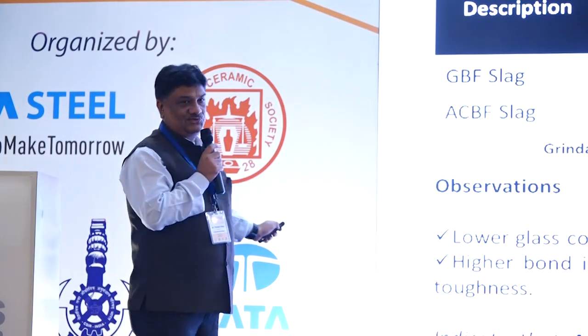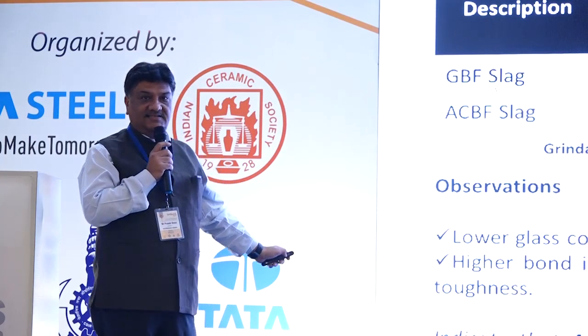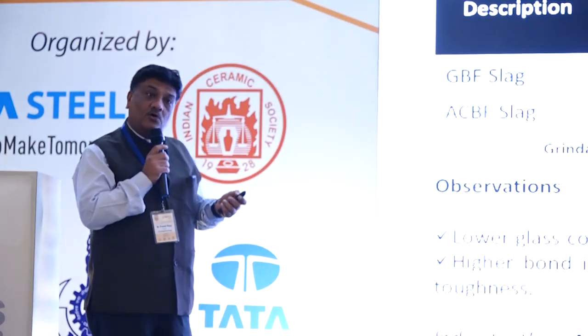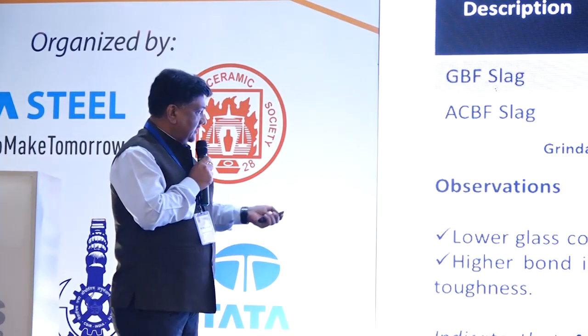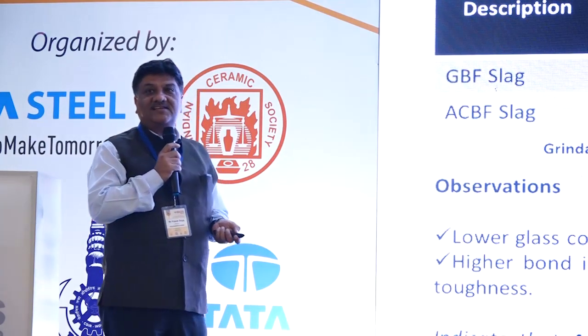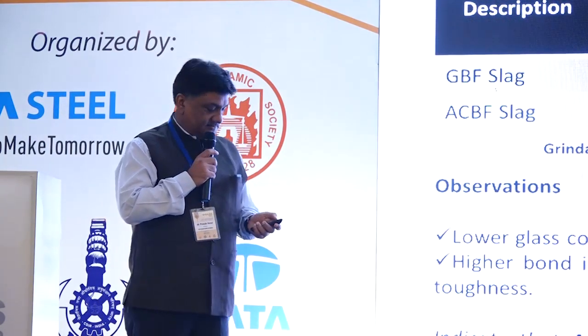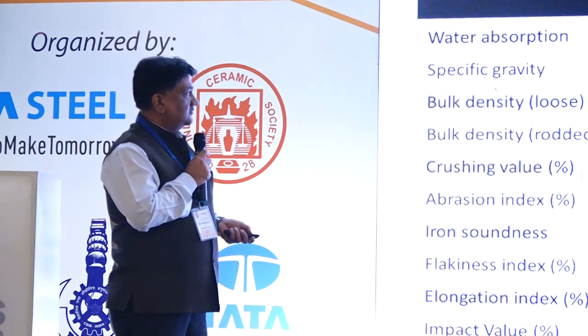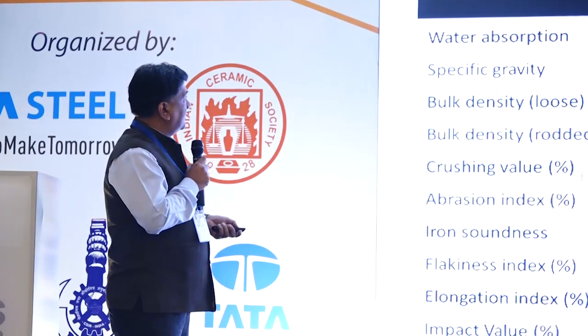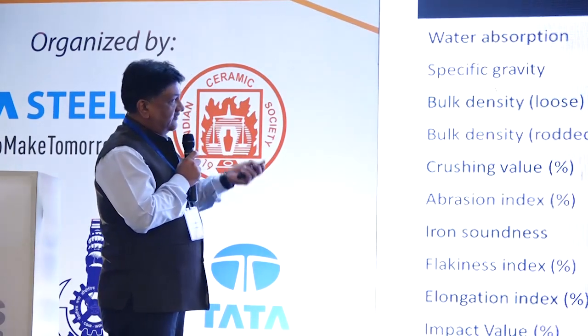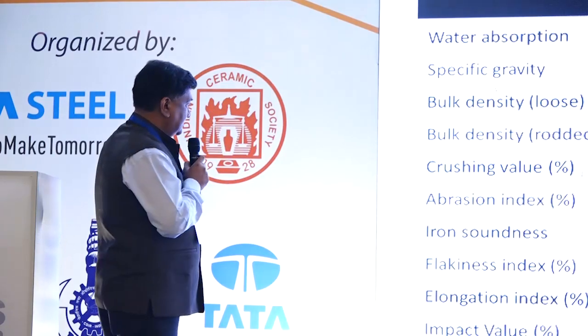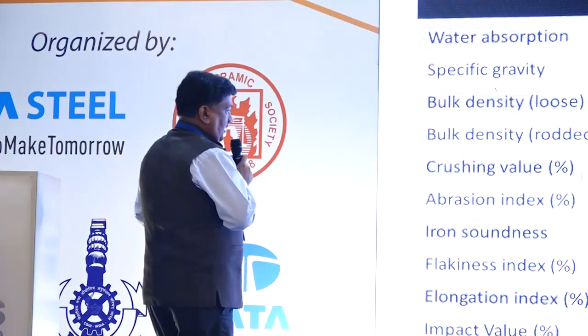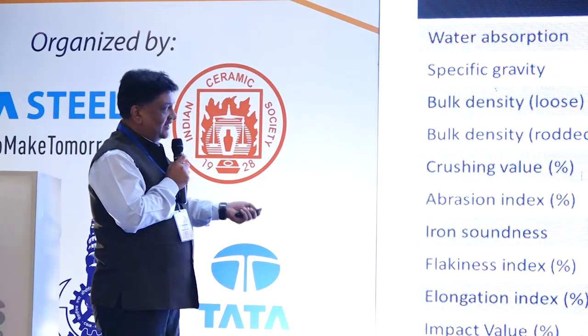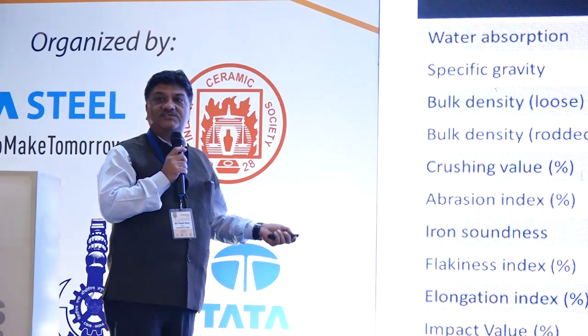So there is a challenge using GBF slag as an SCM, maybe for cement production, or as an SCM for concrete production. But of course, there's a huge opportunity to use it, replacing fine aggregate. Code compliance has been checked with the same aggregate which we got from TSL Jamshedpur. There is a clear indication that we can definitely use it as an aggregate.